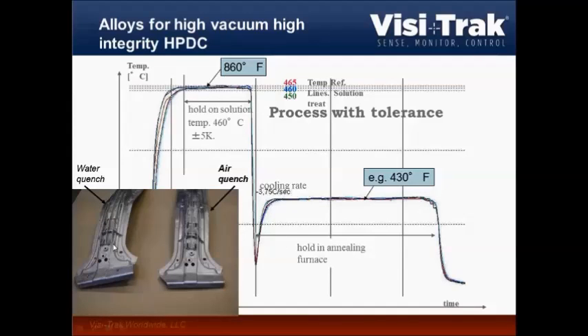If we water quench such a part, thin-walled, large surface, it will just warp like hell, and if we precision air quench, we can keep very tight tolerances. Now the beauty of the high freezing rate in die casting, as we mentioned before, is not only the very fine grain structure that we get, but that also helps that we can really shorten the solution temperature time. And Ray Donoghue wrote a very good paper on that subject, saying that in high pressure die cast parts you can actually reduce this holding time on the solution temperature to below 20 minutes. And that almost doesn't give blistering the time to form. So he has done a lot of work in this area,